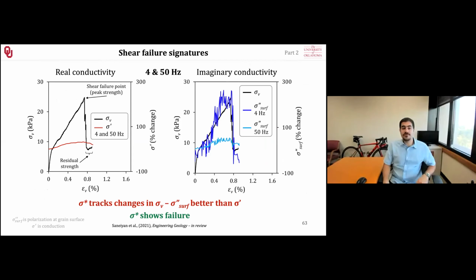We were able to show at both high and low frequencies that the surface imaginary conductivity is very sensitive to the increase in stress as well as the failure. But we couldn't see the same thing for the real conductivity, because even though we were pushing out solution, it is insensitive to the compression of those pores becoming smaller or larger. It is not entirely insensitive; it has a small sensitivity, because we are changing the pores. But the imaginary part is much more sensitive, tracking the same behavior. Our signal initially had a linear part, became nonlinear, and eventually failed our sample. We can clearly see that in our imaginary conductivity signal as well. Very similar, although there is some noise, the overall trend is very similar.